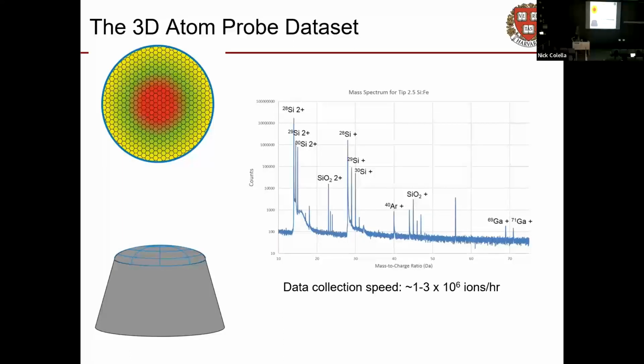And each data point is the position an atom landed and the amount of time it took to get there and the voltage that was being applied at the time. And you put them all together and you get a mass spectrum. Here we go. Here's a mass spectrum. And the resolution is good enough that you can see the different isotopes of silicon. The difference between that peak and that peak is one neutron. So that's pretty good mass resolution.